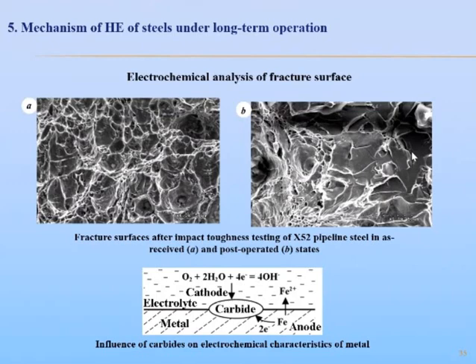And precipitation of carbide nanoparticles causes steel embrittlement and consequently leads to brittle fracture and reduction in fracture energy. And in such circumstances, both intergranular cracking of pipe steel under service and transgranular cracking of post-operated steels under impact toughness testing are associated with this phenomenon. And under such a mechanism of in-service degradation of metal, fracture surface should be enriched by carbon compounds, carbide type, and as it's known, electrochemical characteristics should be sensitive to this enrichment.